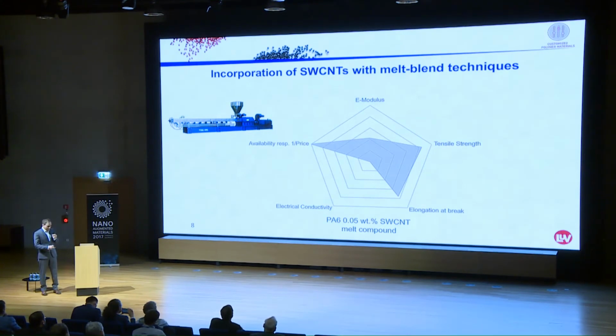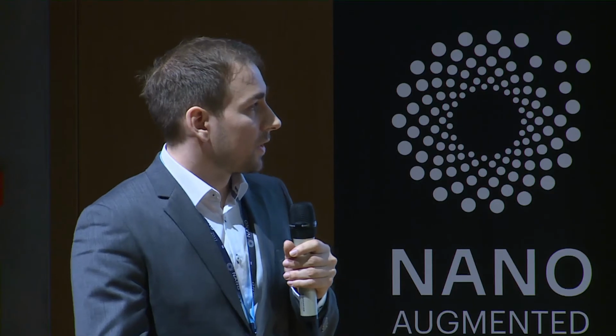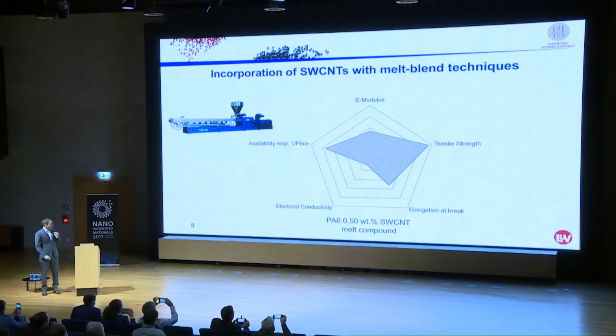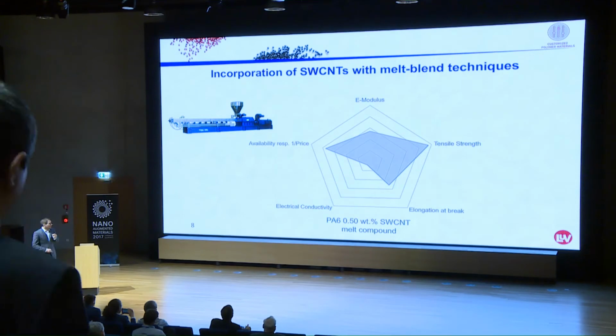The elongation decreases and the E modulus increases, also the tensile strength is increasing. You see here, for me, it was remarkable, just such a low filler grade with an extruder to have such a big effect. And if we keep going, the effect will get stronger and stronger. Now we have to take into account that the costs will increase because these TUBALLs are still kind of pricey compared to polyamide 6.